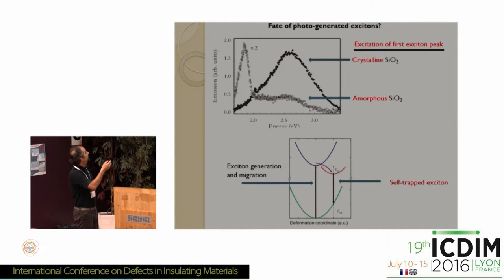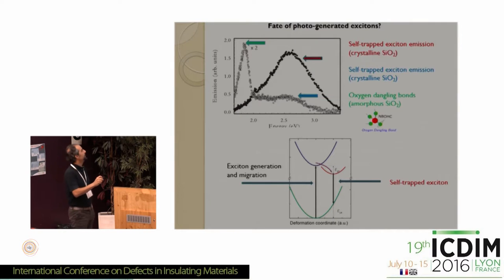So the photo-generated excitons in part get trapped at some point and give rise to the self-trapped exciton emission. However, the interesting fact is that in amorphous SiO2, apart from this emission, you also have this peak at 1.9 eV. Now, the peak at 1.9 eV is known to be the characteristic photoluminescence of oxygen dangling bonds.